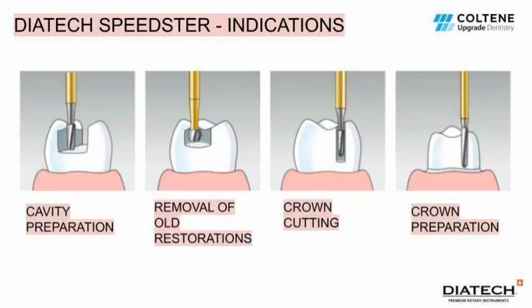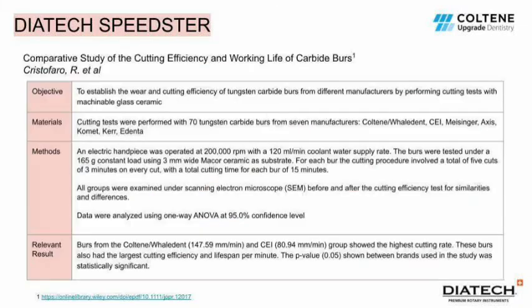DIATECH Speedster can be used in cavity preparation, removal of old restorations, crown cutting, and crown preparation. A study comparing the cutting efficiency and working life of different kinds of tungsten carbide burrs showed that DIATECH Speedster burrs had the highest cutting rate, the largest cutting efficiency, and the largest lifespan per minute. And these values were statistically significant in comparison with all the other burrs that were tested.